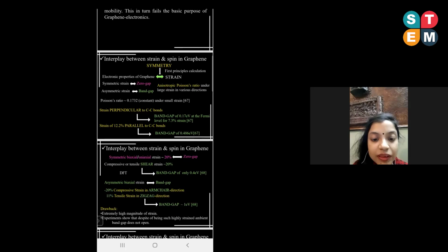has been found that electronic properties of graphene depend on strain, and the strain state of graphene depends on the magnetic state of graphene. We find that symmetric strain has as such no effect on the band structure of graphene. It still continues to be zero gap, whereas asymmetric strain opens up a band gap in graphene. This may be attributed to the anisotropic Poisson's ratio of graphene. That is, the Poisson's ratio of graphene has a tensor form and is different in different directions, and 0.1732 it remains constant under small applied strain.